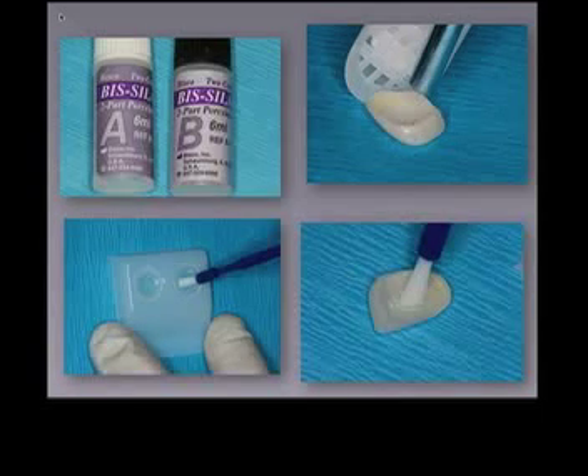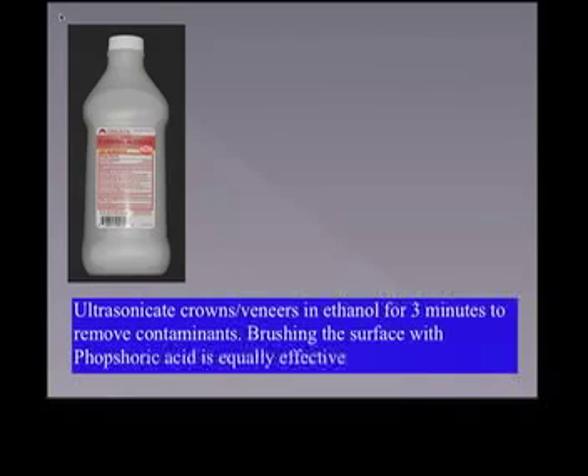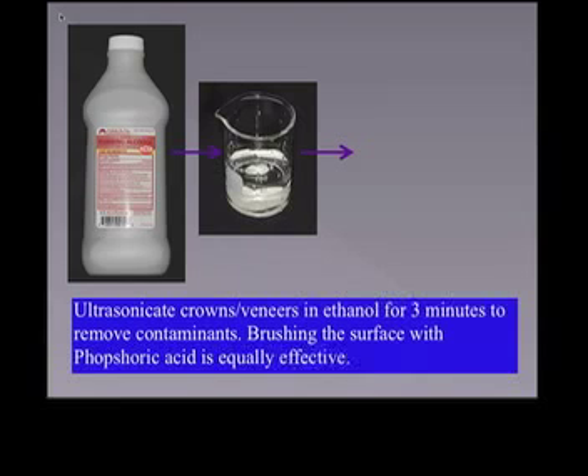Following the try-in, cleansing the previously silanated Emax results in a monolayer of silane in addition to a disinfected surface to bond. We'll use our little technique here that will clean everything up.